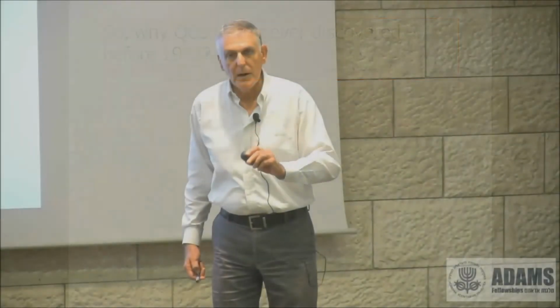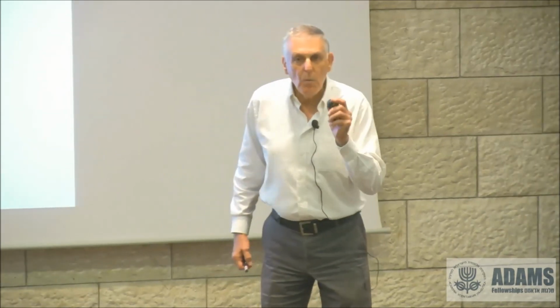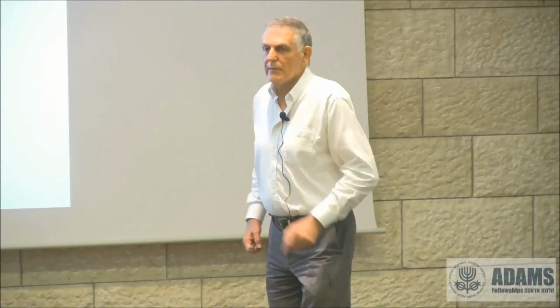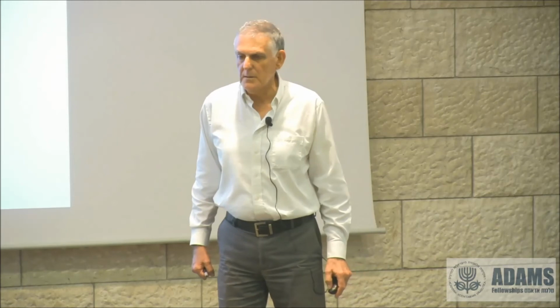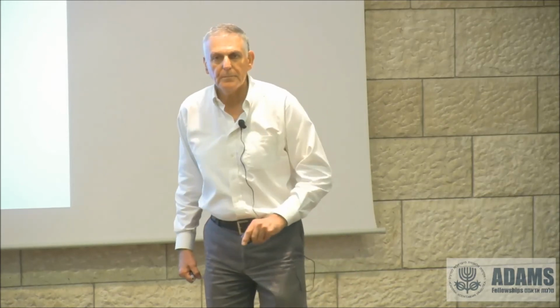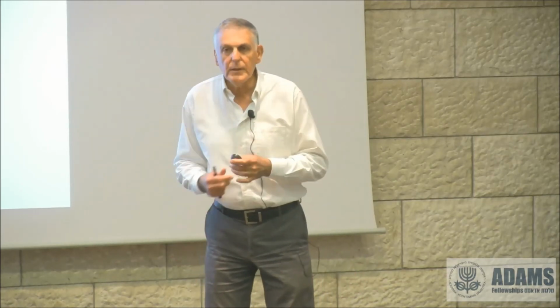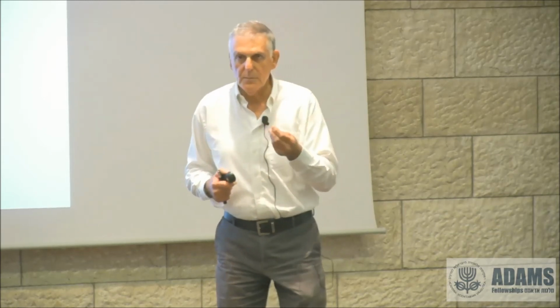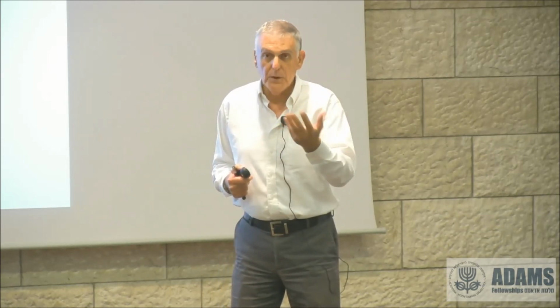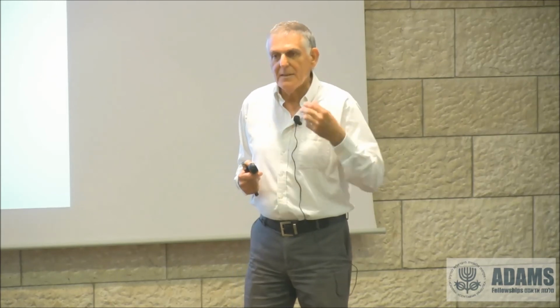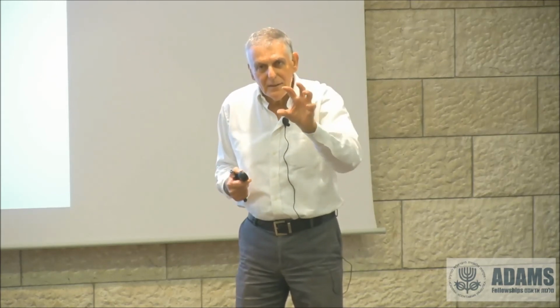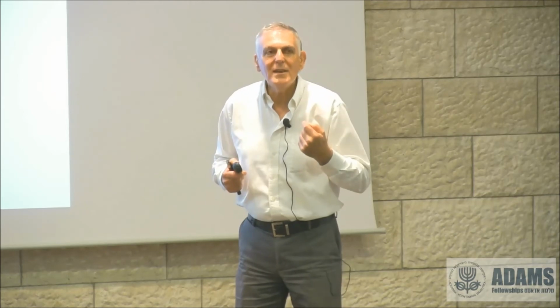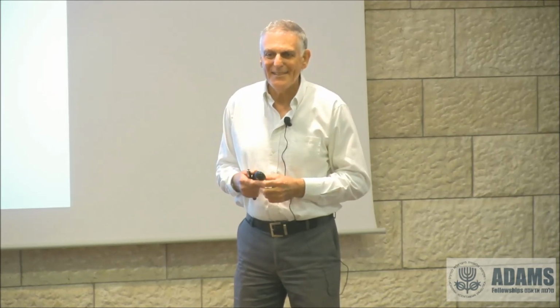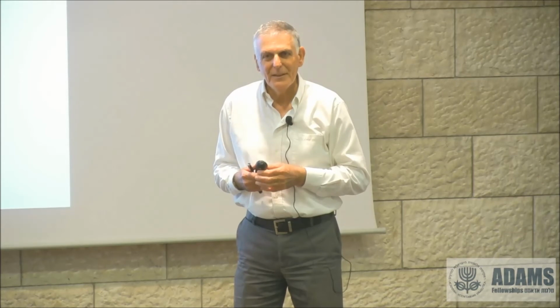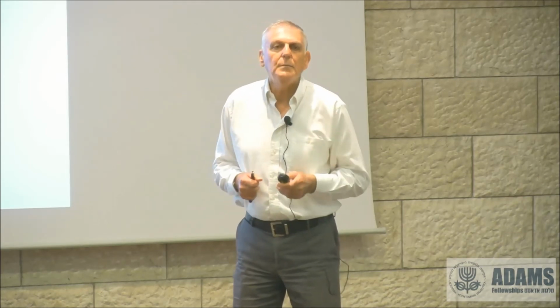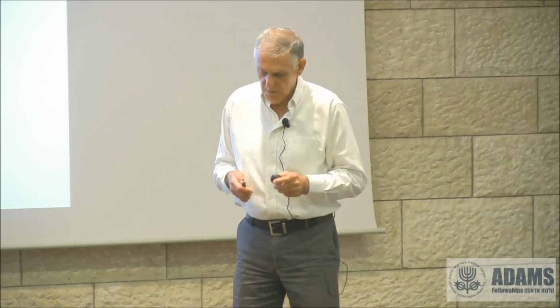And this is now becoming subjective. Number one, quasi-periodic materials had to be discovered by TEM, transmission electron microscope, because they were very small. And if you take X-ray diffraction of a material which is quasi-periodic, it's polycrystalline, you have many little crystals, and instead of points, you see rings. And you cannot see the 5-fold rotational symmetry. You lose the rotational symmetry. So it had to be done by TEM. So TEM is rule number one.